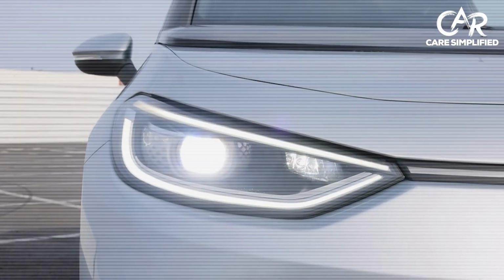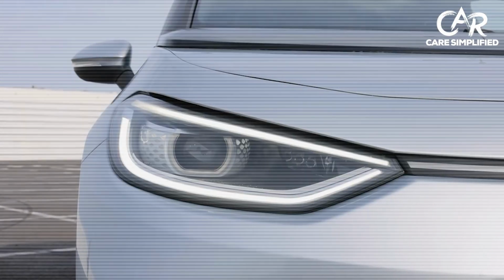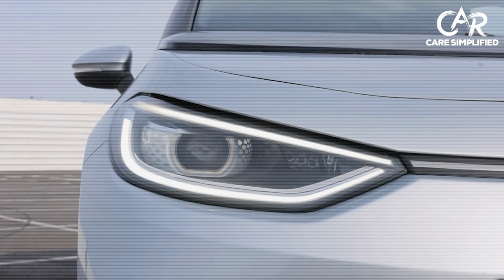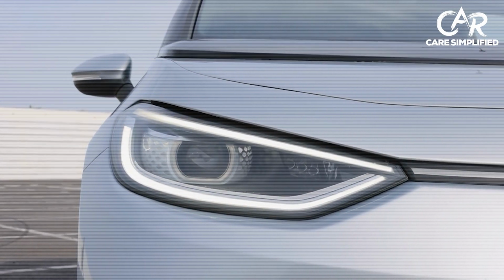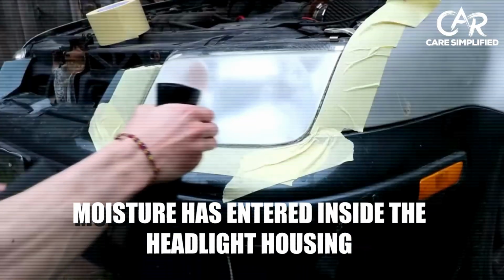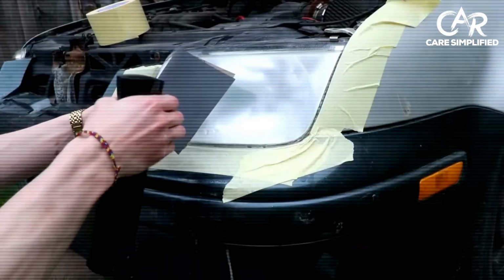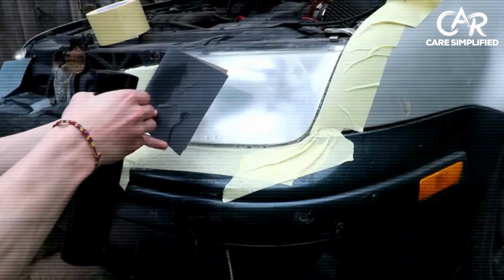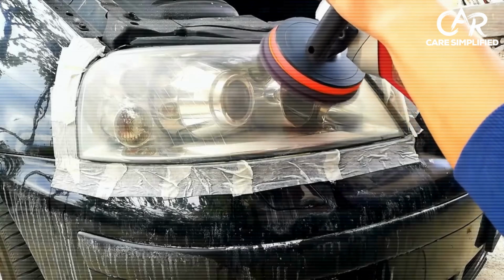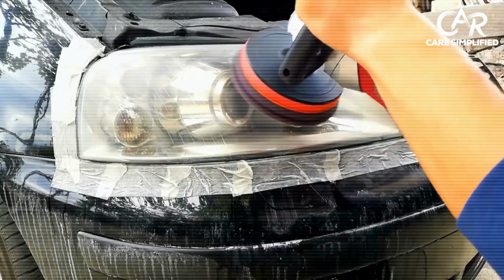Now, this restoration works on the vast majority of headlights, but there is one condition where it can actually make things worse. If moisture has entered inside the headlight housing through a failed gasket seal, the cloudiness you see is coming from the inside, not the outside. No amount of external sanding or coating will fix an internal moisture problem. You need a seal replacement, or in some cases, a full assembly swap.